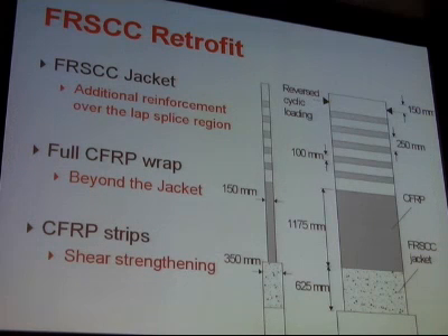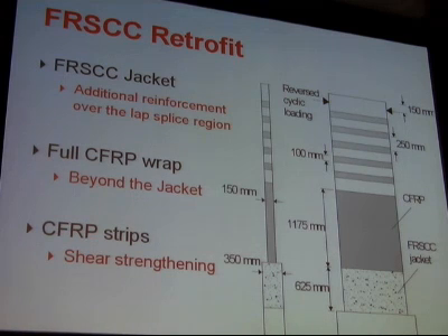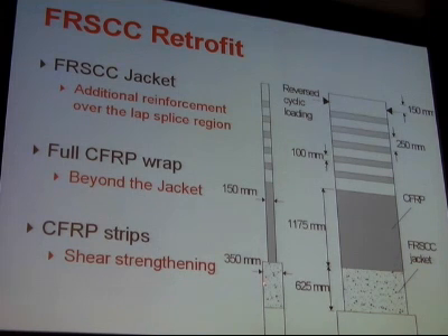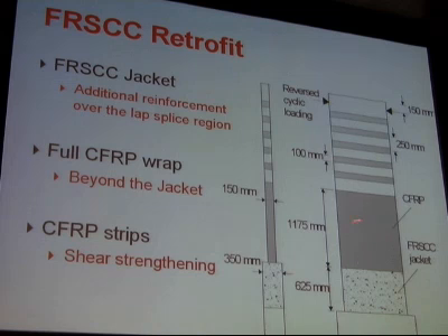The other type of retrofit that we did was a more serious retrofit job. In fact, we took the 2 specimens that had failed under reverse cyclic loading and actually repaired them, but it's also representing a retrofit procedure where we put some fiber-reinforced self-consolidating concrete over the lap splice region, adding it to the wall, not lengthening the wall because architecturally that's sometimes very difficult to do with the retrofit. Then above this, we have the CFRP wrap and we have the shear straps.